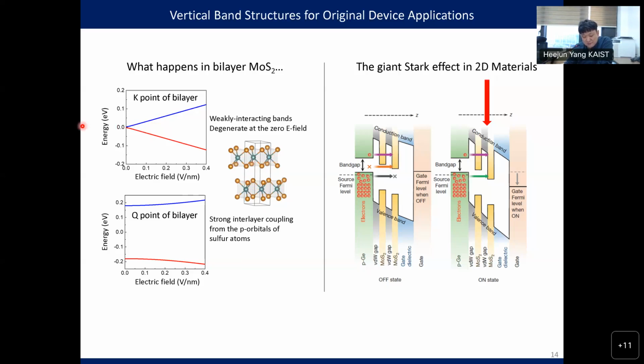But if we apply a vertical electric field, we have some electron displacement, and then we can break the degeneracy. Now we have sort of a voltage drop between the two layers. It's because the electrons of these molybdenum atoms are not interacting seriously. But what about these sulfur atoms? They contribute Q-valley electrons. And you see they are quite close to each other. Chemically, if we approach two atomic orbitals, we have bonding and anti-bonding features. This is an important thing. So we have a bonding and anti-bonding split of the band, because they are interacting a lot. So this voltage drop picture is valid for K-point electrons.